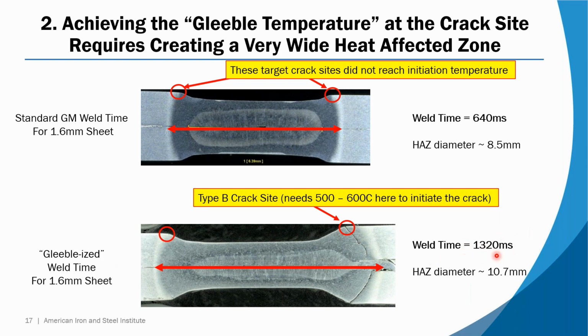So let's double the time. That's what we're doing here basically. And then when we did that, the heat affected zone diameter jumped up to 10.7 millimeters, and that gave us a suitable temperature for creating this crack. Okay, and you can see little superficial cracks beginning to form on the opposite side. So that's basically the strategy with parameters.